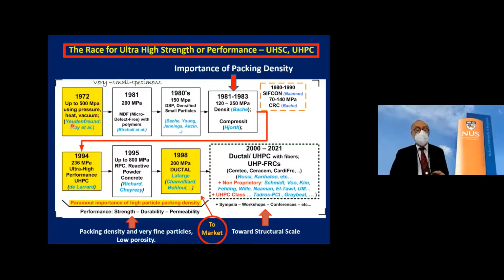One of the first studies here, Yudenfreund and Roy, in 1972, published a study that they had achieved 500 megapascal. And this is very exciting, of course, except when you went and looked at the details, they used an 8 millimeter or so specimen. They heat cured it, used pressure, a vacuum, etc. So it was a good record if you want, but it was not very practical because you very well know that if you have a very small specimen, when you go to scale, things change completely.